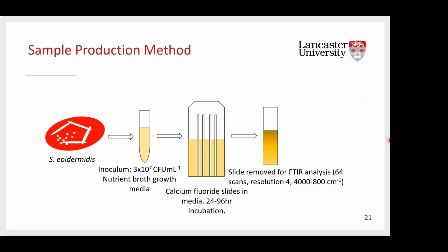Quickly, just to demonstrate my biofilm growth method, for reference, we use a fairly simple glass growth chamber, and a nutrient broth is maintained at a particular concentration. We put calcium fluoride slides into this broth and then incubate it for the desired time periods. For our FTIR work completed to date, samples are removed at the incubation period and transferred to a drying chamber to partially dry the samples. In the early stage of testing, this allows the removal of the bulk of hydration, which can sometimes overwhelm FTIR spectra, which can then lead to masking vital signals.